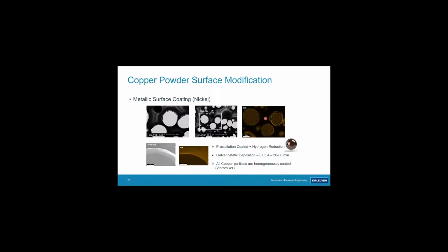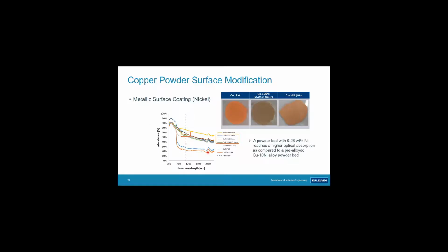The first attempt we did was coating copper powders using a precipitation method, so that we would precipitate nickel hydroxide and then do a hydrogen reduction. And you see the EDX nickel maps, they clearly show that every particle is nicely surrounded by a nickel layer. So in that sense, our particles were nicely coated, and you also visually saw that. So this is the original copper powder on the left-hand side here. And then once you coat, the color really changes.